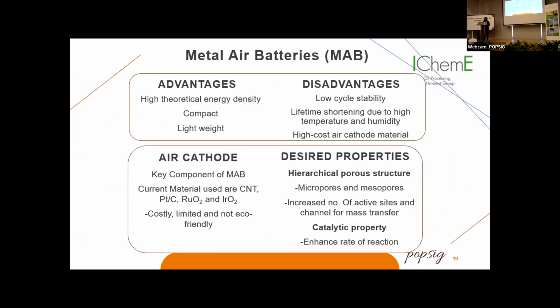So there's a lot of advantages to metal air batteries, such as the high theoretical energy density. It is also lightweight and compact, as it uses the oxygen from the air, which helps to significantly cut down the size and the weight. However, there are several disadvantages, such as the low cycle stability. It also succumbs to lifetime shortening if it's exposed to high temperature and humidity. And most importantly, it uses high-cost air cathode material.